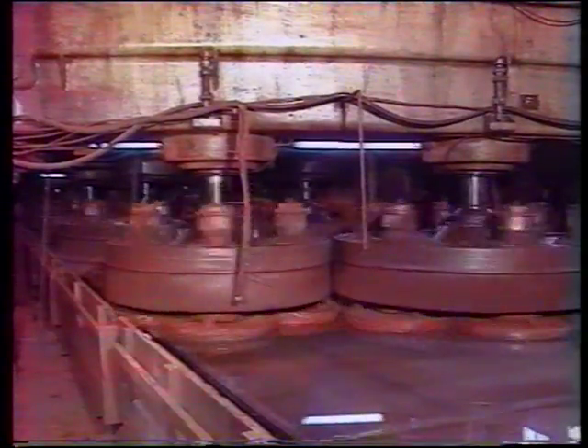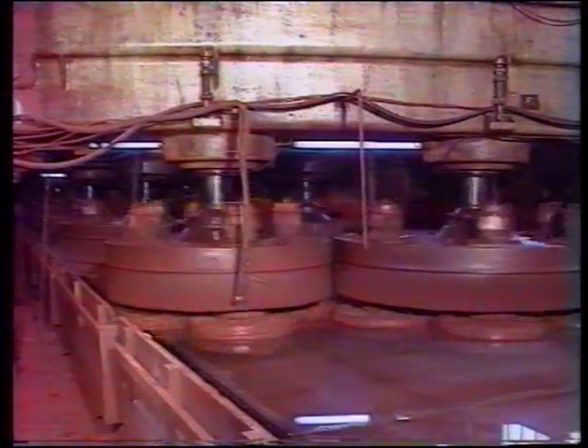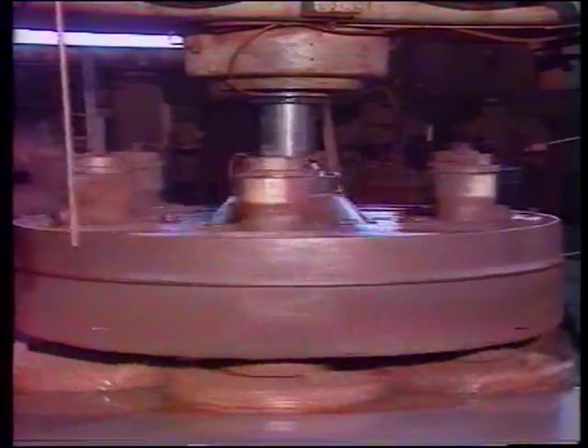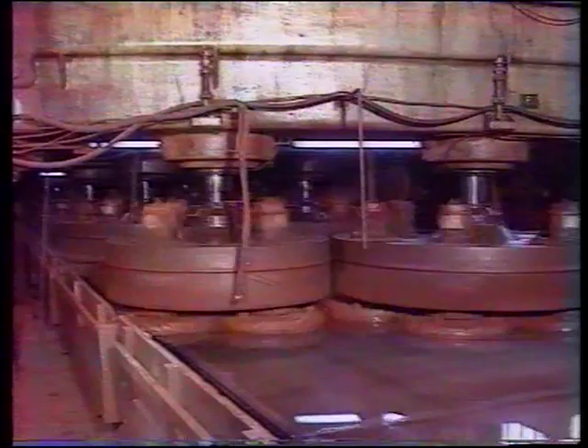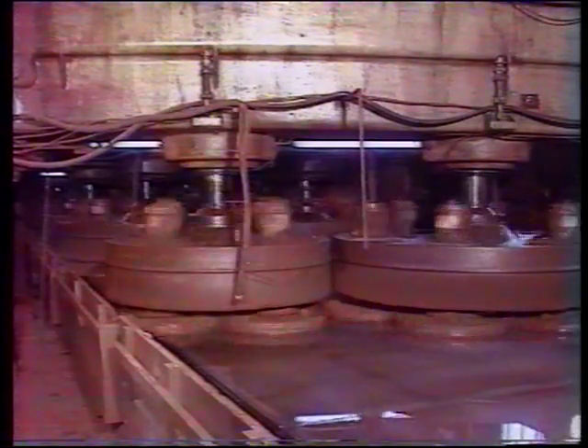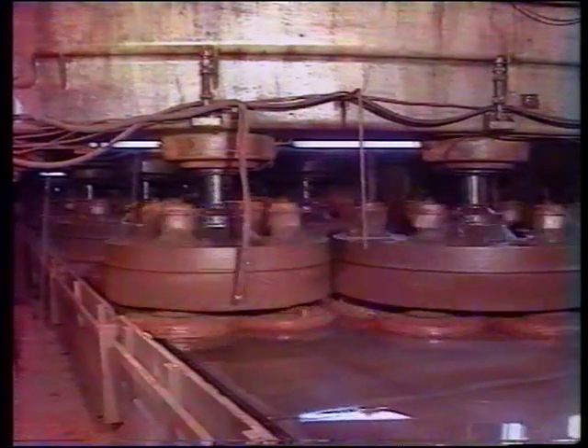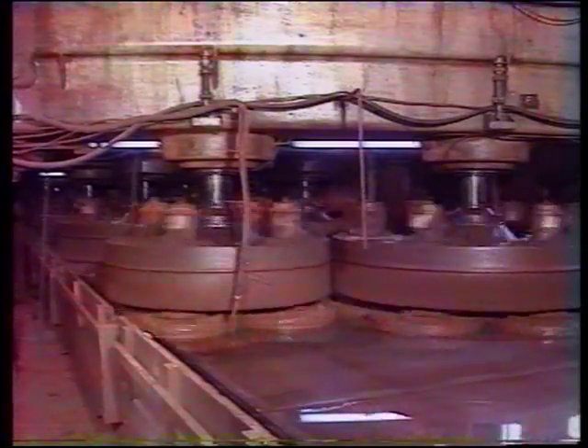Now on to the polishing section. Each polisher head has 2 spindles, one carrying 4 pads and the other carrying 6. The pads are 1-inch thick polyurethane and need changing about once a month. The 6 and 4 pad spindles are alternated down the line to form a pattern that gives a uniform polish across the full width of the plate. Rouge is fed onto the glass upstream of each polisher. There are 20 heads, and the last 3 are fed water only to aid the glass cleaning process.